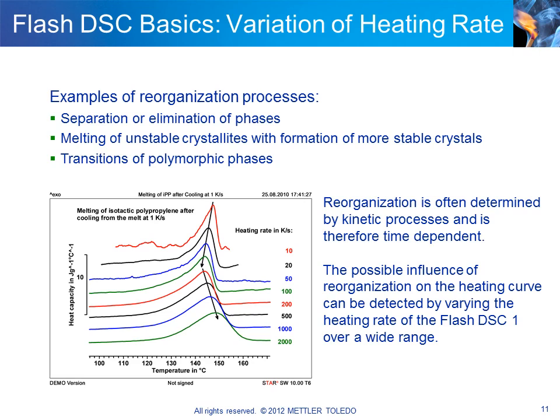If no reorganization occurs, one expects the maximum of the melting peak to shift to higher temperatures at higher heating rates. This is the case at heating rates above 200 degrees per second. At lower heating rates, one observes the opposite behavior. The lower the heating rate, the higher the melting temperature. In this case, the time available during heating is long enough for more stable crystals to form that do not melt until higher temperatures. The lower the heating rate, the higher the melting temperature becomes and the less information the melting peak contains about the original sample.